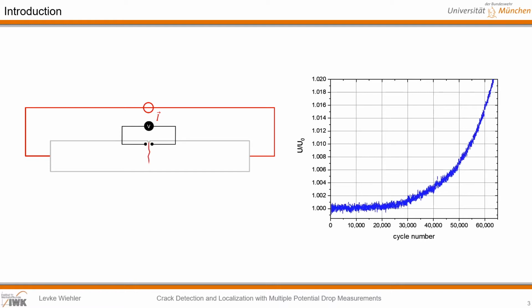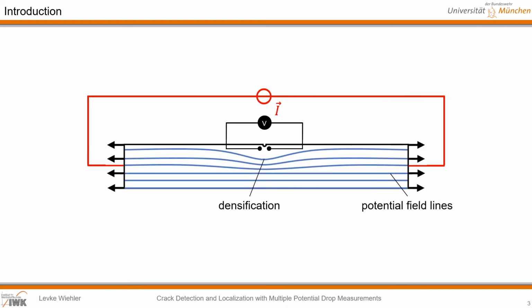As soon as the crack grows, as seen on the specimen, the measured potential difference increases until the failure of the sample. Due to a propagating crack, the cross-section of the specimen is reduced, leading to a densification of potential field lines. To give you a brief overview of where we are in the presentation, a short outline follows.